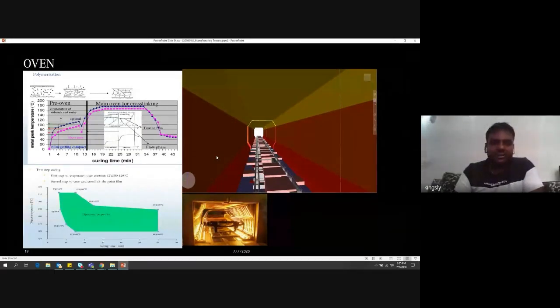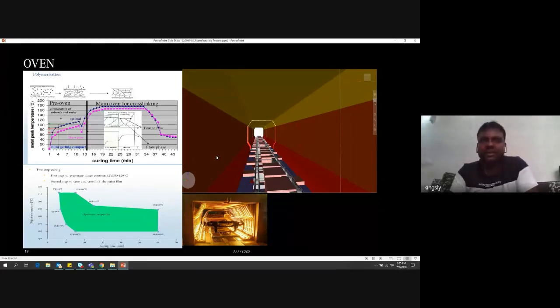The next process for painting is the oven. Whenever you do the painting, any coat, say e-coat or base coat, primer coat, we have to send this car into the oven. So what is an oven? An oven is nothing but a heat chamber, because each paint material depends upon the supplier's paint manufacturer recommendation. Whenever we do the painting, we have to do the polymerization. Why do we have to do it? Because we need a minimum of around 10 years of life for this paint. Some OEMs give a 30 years guarantee, some give 10 years for paint corrosion, and some OEMs give 3 years.